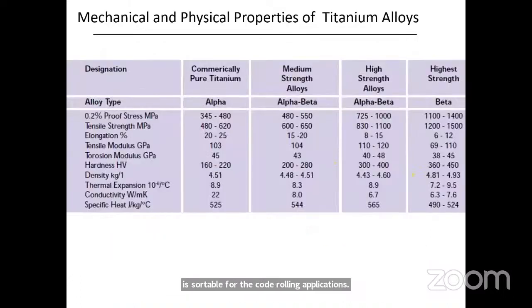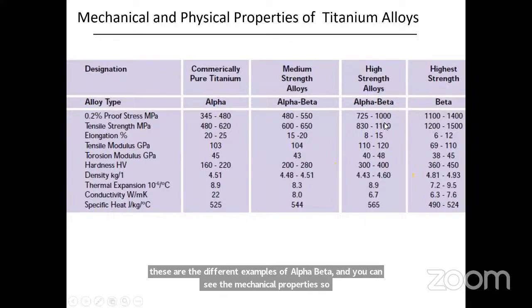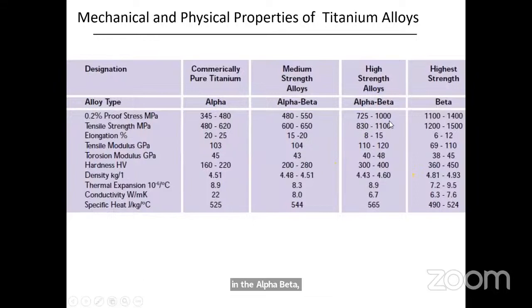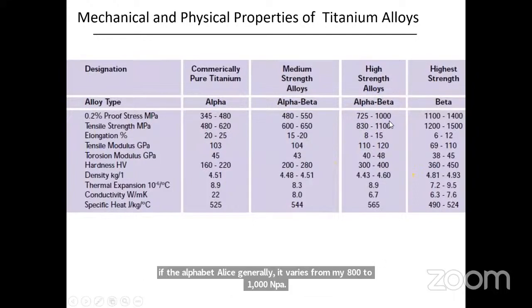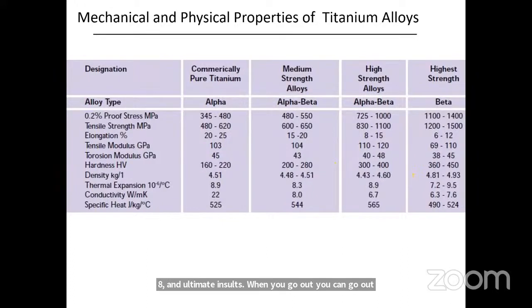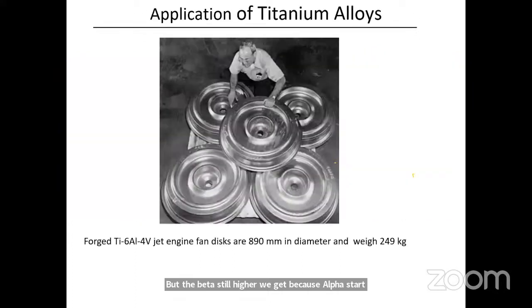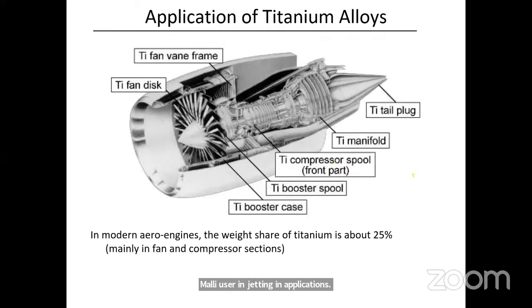So these are different examples of alpha, alpha-beta and beta alloys, and you can see the mechanical properties. The alpha beta alloys generally vary from 800 to 1000 MPa yield strength, and ultimate tensile strength can go up to 1100 MPa. But beta alloys give still higher strength because alpha starts precipitating out during aging. These are examples of titanium 6 aluminum 4 vanadium alloy used in jet engine applications. These are jet engine fan discs you can see here.